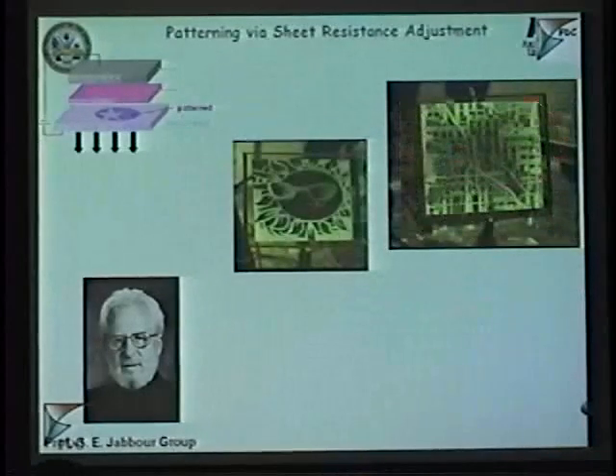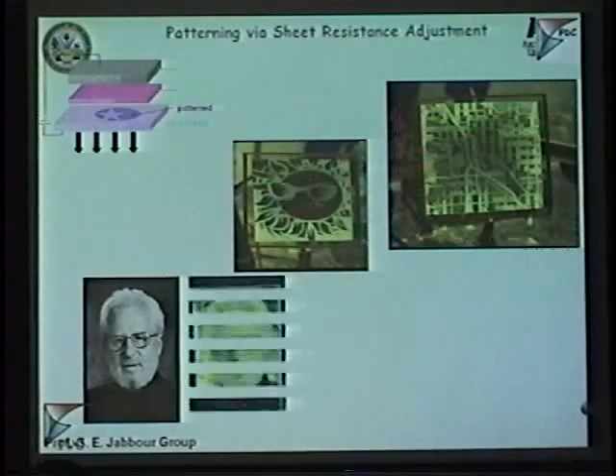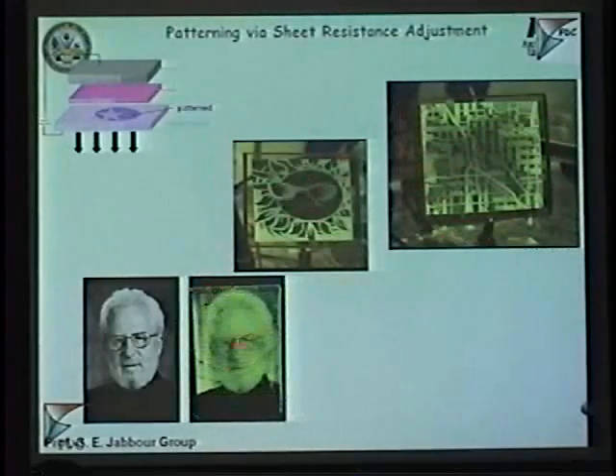There you go. You see the map of Tucson, the sunflower, and then this is the picture of Alan Heeger. The reason with these bends, and these are dust particles from our processing in the room environment. We're not doing this in a clean room. And then this bend here is the student, when they did this, they did it straight on the plastic substrate without putting a backing. When you spin coat, the substrate bends, so you see these comets like so.